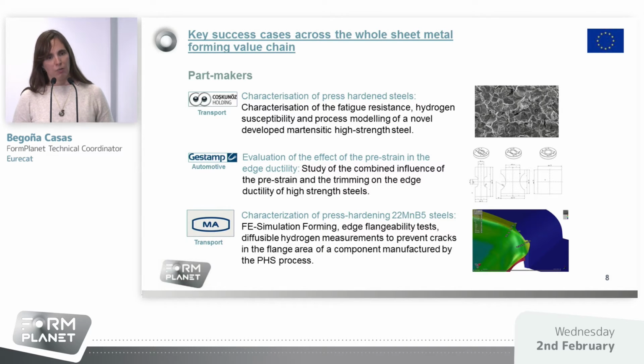Another company of the open call was MA for transport applications. We characterize press hardening steels. To do that, we performed finite element forming simulation, edge flangeability tests, and diffusible hydrogen measurements, with the idea to prevent cracks in the flange area of a component manufactured by the press hardening steel process.